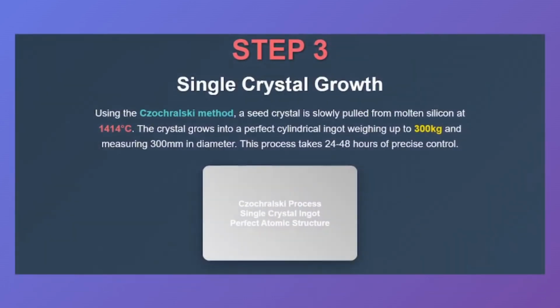Step 3. Single crystal growth. Using the Czochralski method, a small seed crystal is dipped into molten silicon and slowly pulled upwards, rotating as it goes. This forms a flawless cylindrical ingot up to 300 mm in diameter and weighing over 300 kilograms. The process takes up to 2 days of precise temperature control.